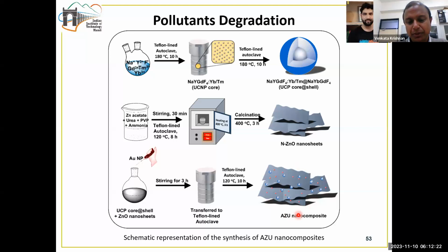So this is how we prepared this upconversion material combined with the N-ZnO nanosheets and decorated by gold nanoparticles. This is a ternary material which we prepared using a simple mixing technique. The catch is that the stirring time determines how well all these materials are distributed, and we are taking these materials in appropriate weight percentages. So that's how we prepared this material.